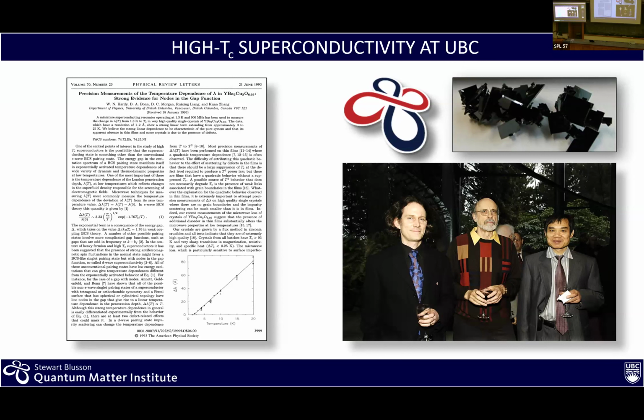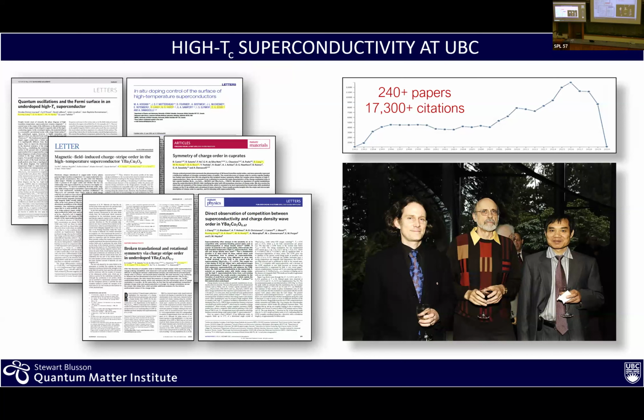And so they were able to show in this '93 paper that indeed the behavior is consistent with the presence of nodes in the order parameter. And in order to be able to do that, growing the best possible crystal was key. Otherwise, impurities would have masked the behavior and made the experiment impossible. This was the beginning of a big effort for UBC, an effort that then resulted in these samples being distributed all over the world for all possible experiments. So really, if you look at numbers, they fueled hundreds of papers over the last few years, and received tens of thousands of citations for this specific work. And this is really what put UBC on the map as far as this kind of work.